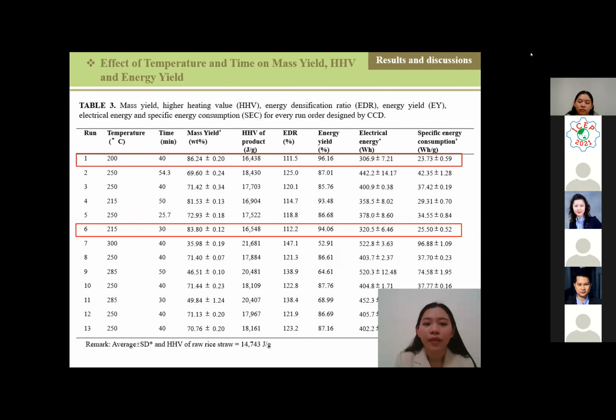Table 3 shows the mass yield, high heating value, energy densification ratio, energy yield, electrical energy, and specific energy consumption for the 13 runs designed by CCD. It was found that mass yield varied from 35.98% to 86.24%. It was reported that torrefaction gave biomass valorization because of molecular reduction and decomposition of hemicellulose. An increase in temperature and time resulted in lower mass yield and higher high heating value.